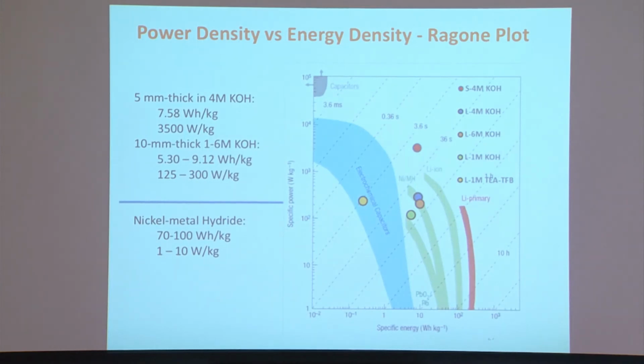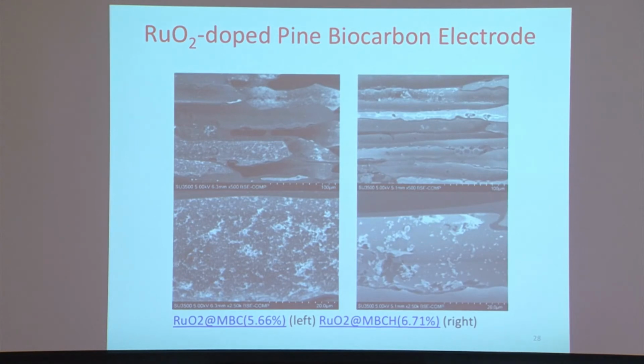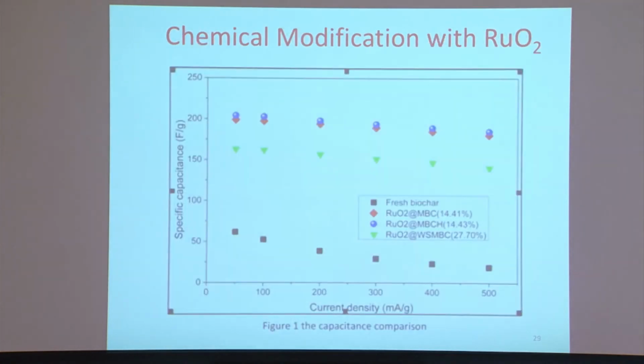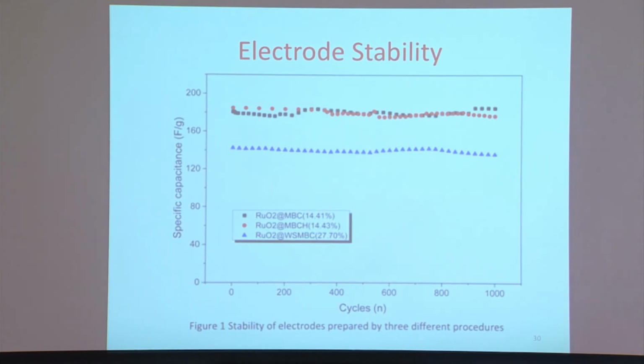We also tested our cells under different conditions with different electrolytes. What we found is that our cell has a much higher power density than a battery, which is expected, but the energy density is still lower than the battery. So in order to increase energy density, we modified these carbons with ruthenium oxide. This is the result. The black one is untreated, and the colored ones are treated. You can see an increase of almost 4 times. We also tested the electrode stability up to 1,000 cycles, with very stable performance.